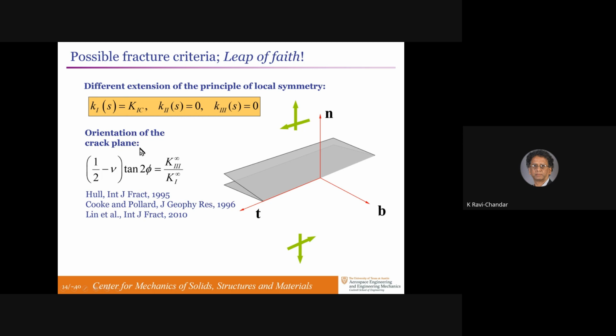This is very easy to impose. The angle at which the crack would tilt based on this is calculated by this simple formula for plane strain. That means the crack should do that. The parent crack is in gray. The daughter crack will be the shaded orange color. But this is a criterion that's not possible to be imposed locally everywhere. It doesn't have translational invariance. If I move to the right, it'll violate it.